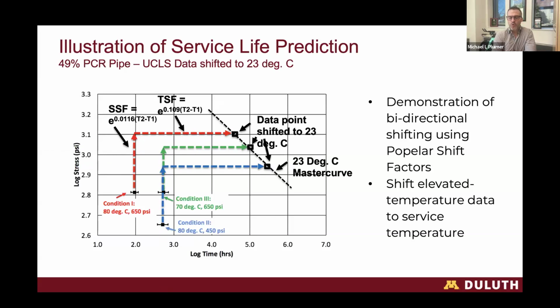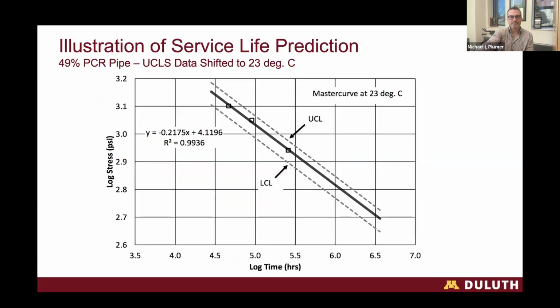It's actually a little bit warmer than what we would see pipes in Minnesota buried at, but it is maybe a temperature that we'd see a pipe in Florida buried at. If we're at colder temperatures, this curve would shift even further to the right. So this is a pretty conservative model that we're using at 23 degrees C. So based off of that model, then we could do this test for any different material with any blend of recycled content and predict how long that pipe would last at various stress conditions.